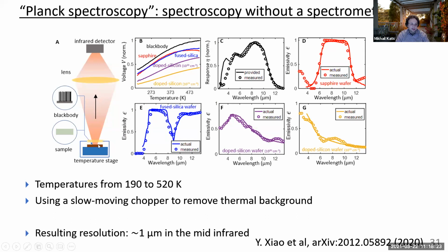And then we can either put a sample there or we can put a black body reference there. And we take that output and we just send it to an infrared detector. I'm using a lens here. In principle, the lens is not necessary. You could just put the detector really close to the sample, but we decided to do it this way, just to make sure that you don't have some weird conduction or convection from the sample to the detector. So we just put it really far away, and we built an imaging system. And here are the experimental results.